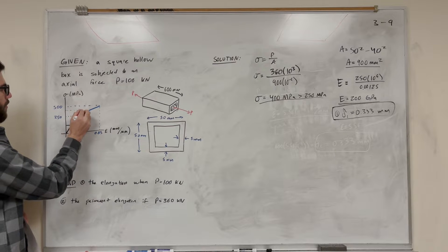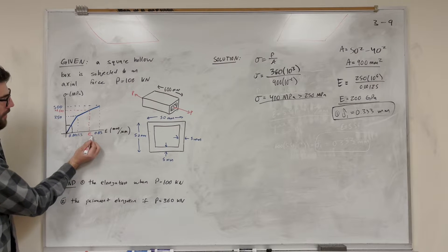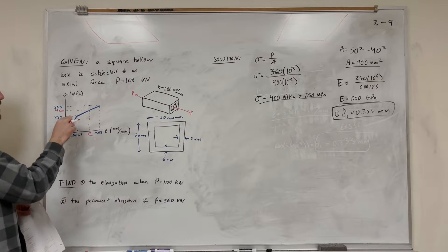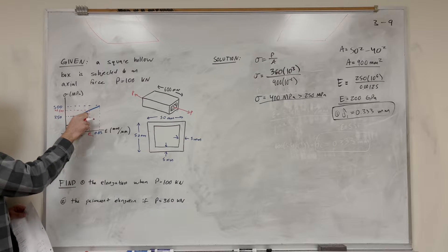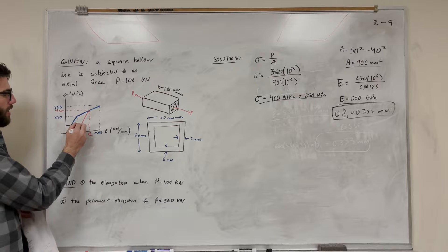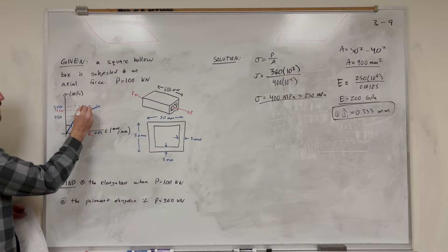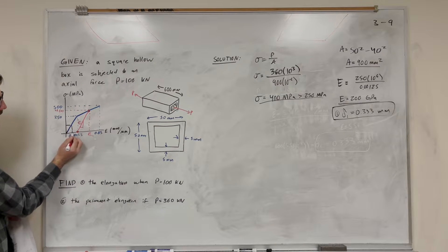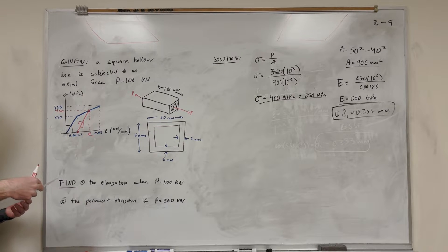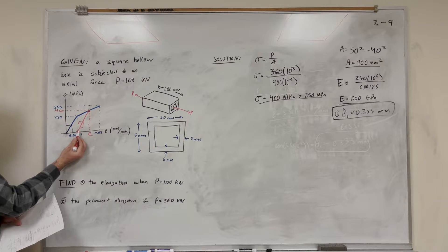So let's draw 400 on this stress-strain line — 400 is probably about here. Our goal is to find what value of epsilon corresponds to this point. When we enter past the elastic region, we follow the stress-strain diagram along this line. But when we let go, we go back down like this, and this slope is going to be E — our modulus of elasticity that we found. So if we can find this point, then our goal is to find this strain value, because that distance is our permanent elongation, or permanent set.